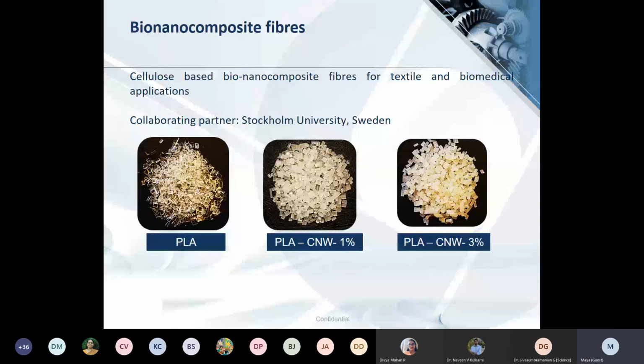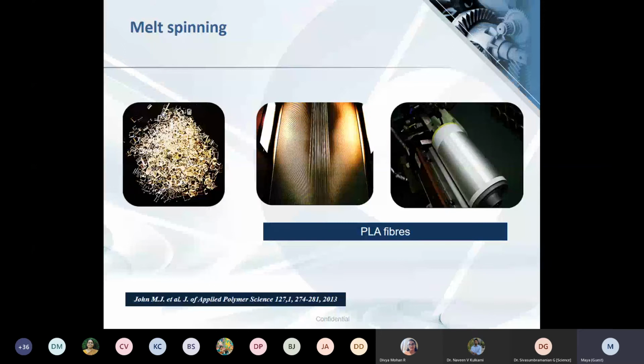So here the idea was to develop bio-nanocomposite fibers from cellulose nanowhisker and polylactic acid. The first step was to prepare a master batch of polylactic acid and cellulose nanowhisker, and this was then placed in the extruder and dry mixed with PLA to get the ratios right. Here you can see the picture of the extruded pellets, and these extruded pellets are then placed in the filament extruder to get the PLA fibers. As you would know, nanocomposites you would usually get in the form of either dumbbell specimens or rectangular specimens. But here you have a nanocomposite which is in the form of a fiber, and the nanocomposite is cellulose nanowhisker reinforced PLA.